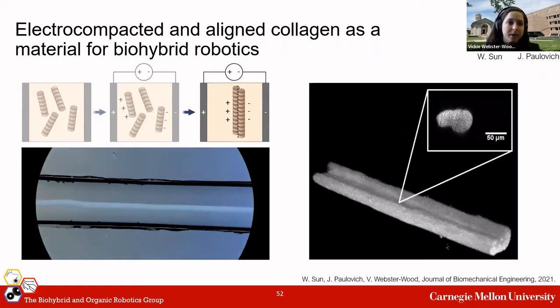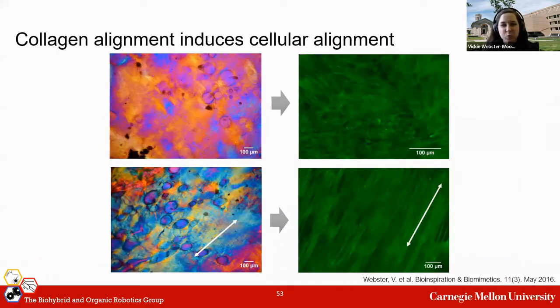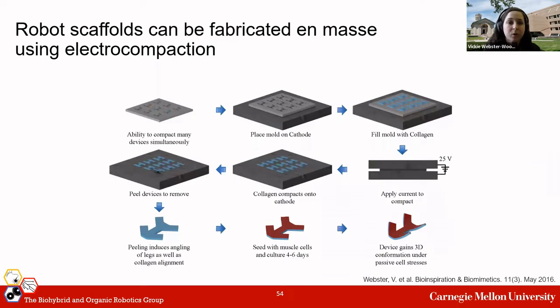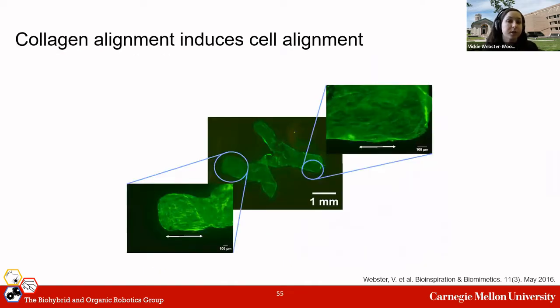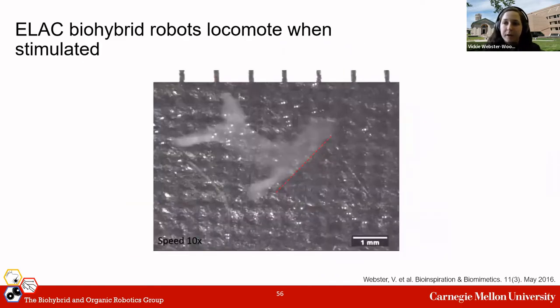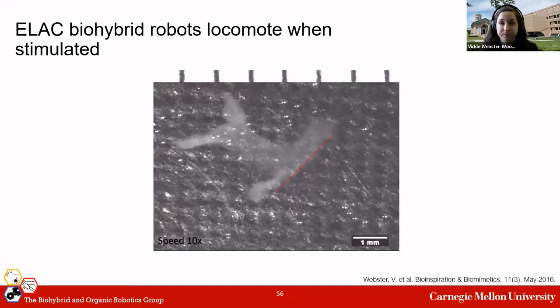For those of you not in the biomaterial space, collagen is an extracellular matrix protein that muscle cells really like to attach to. And we can use the collagen to align muscle that we grow on top of it with the degree of alignment depending on the alignment of the underlying material. During my own PhD, I demonstrated that we could fabricate robot bodies using this approach en masse, and that they did indeed result in alignment of muscle cells on these substrates. Using this approach, the robots even moved in response to electrical stimulation.